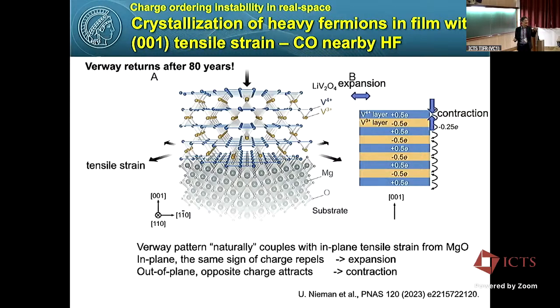So after 80 years, Verwey returned back to the scene. And of course, it is a stack of 0.5 minus, and the same charges repel each other. So it's natural to have tensile strain stabilize this Verwey type charge order. So at least one charge order state is nearby the heavy Fermion state.